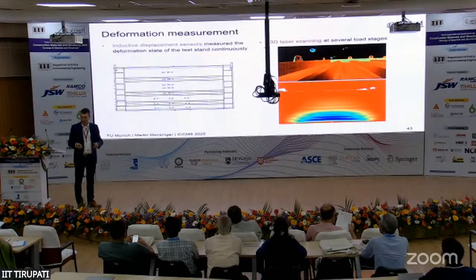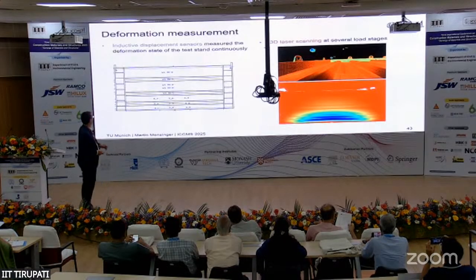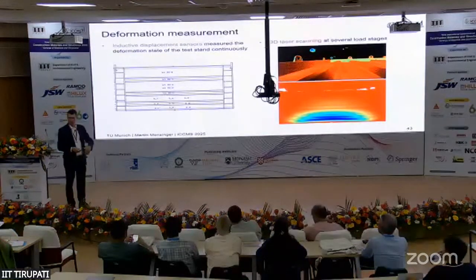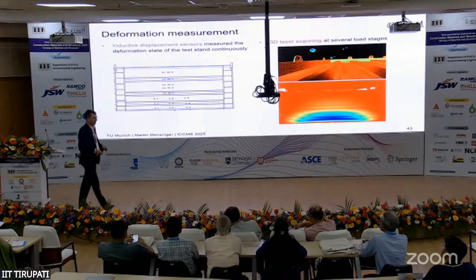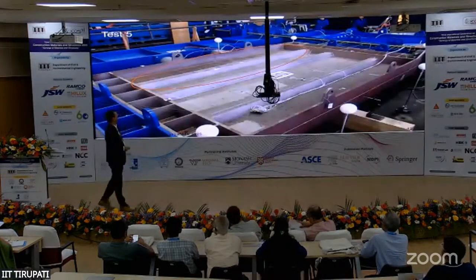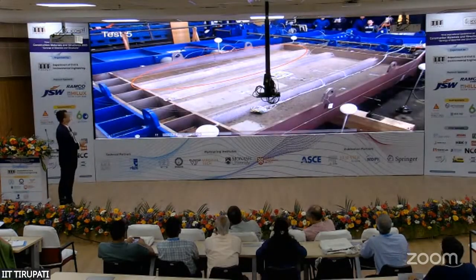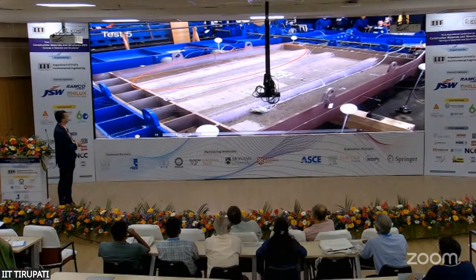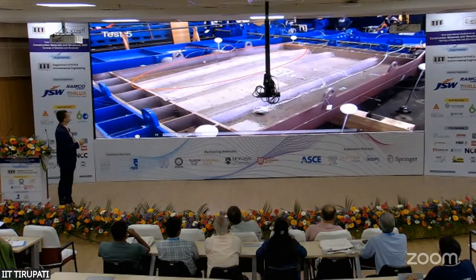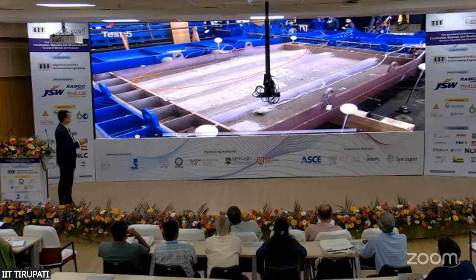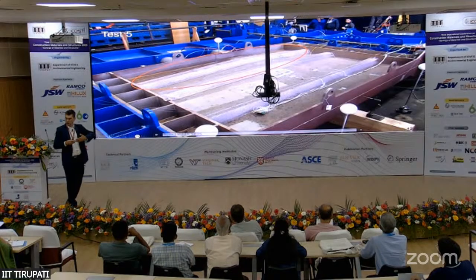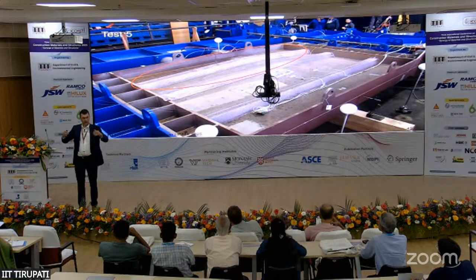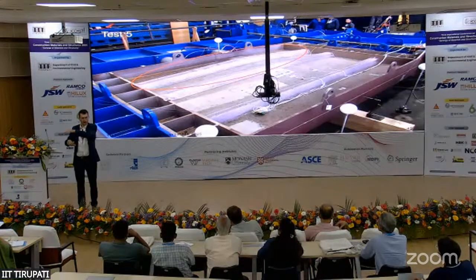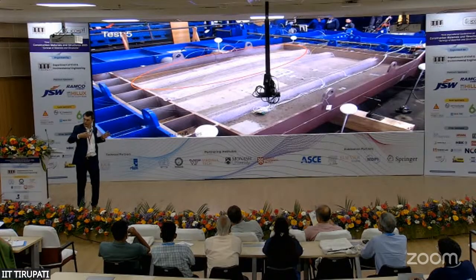quite a lot of other measurements like inductive displacement sensors, strain gauges, and optical fiber. I will not talk about that here because for us it's more interesting to have a look at one test. This is one typical test specimen, and I would like to ask you to focus on this. At the beginning we saw that in this local buckling field, the first buckling field, initially due to this load introduction of the X-force, we introduced a multi-wave buckling pattern, and this buckling pattern in the next step acted as a stiffener for the cross-directional load.